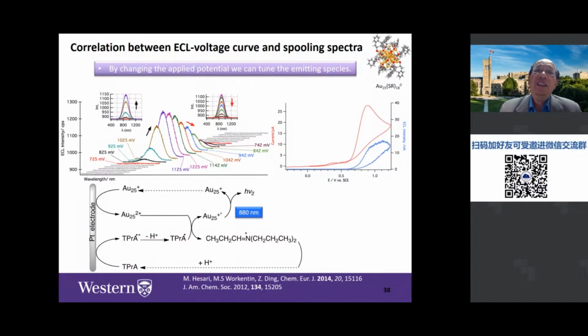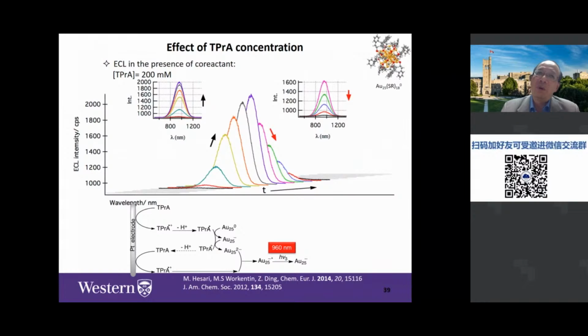So these two voltages just tell us that by changing the applied voltage, we can tune the emitting species. That means 960, 880 nanometers, so different excited states. So now we can define this gold 25 as a kind of smarter material. And with different stimuli, we can get different responses.